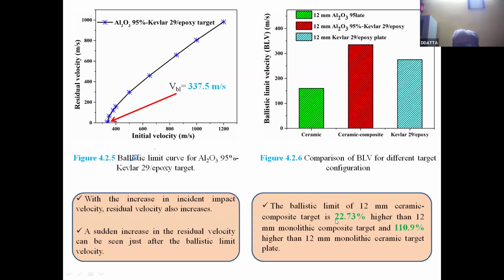The ballistic limit velocity is 22.73% higher when it is ceramic composite compared to only composite, and 110% more when compared to only ceramic. So although defense people are a little hesitant in using ceramic, ceramic gives a better result in the case of ballistic limit velocity. Here for Al2O3 95, ceramic and Kevlar, the ballistic limit is 337.5.